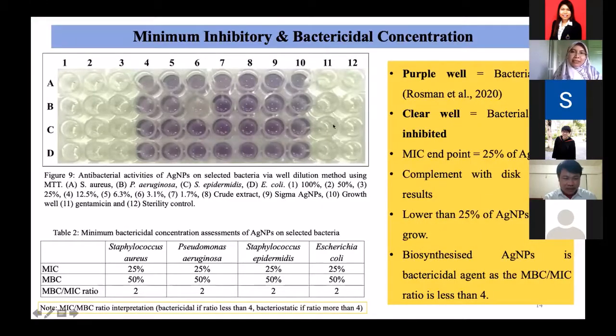So from the MIC and also MBC analysis, we confirmed that we need to use 50% up to 100% concentration to get the highest effects. And from the ratio, we found the MBC to MIC ratio of our sample when tested on the bacteria was 2. That means it is bactericidal and can kill the bacteria.